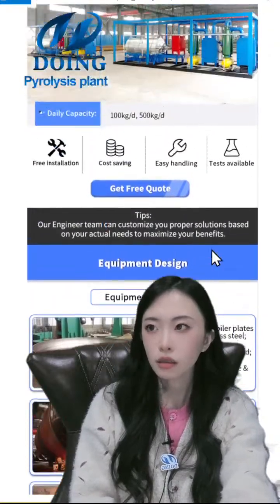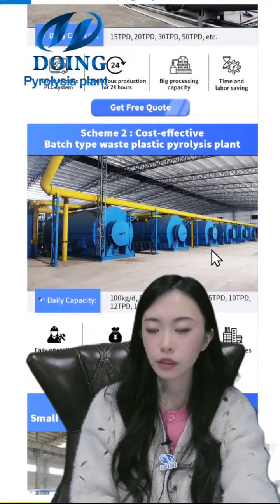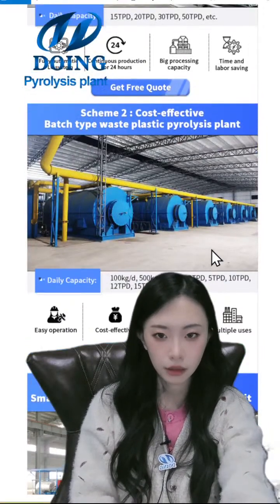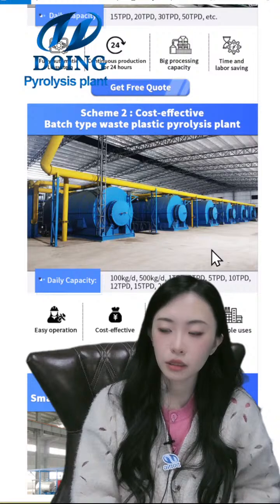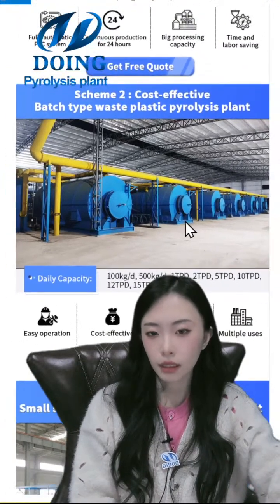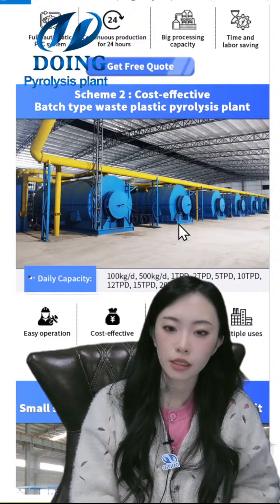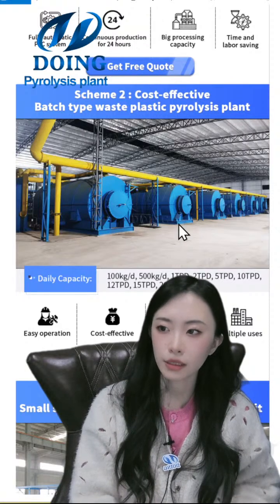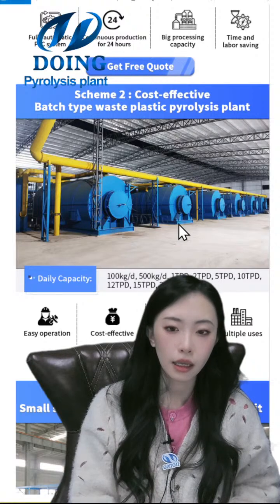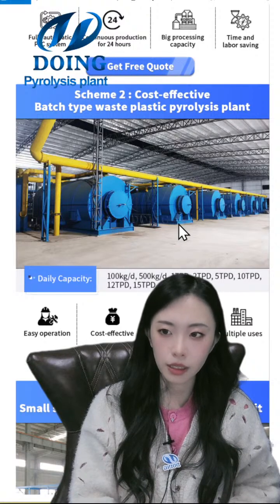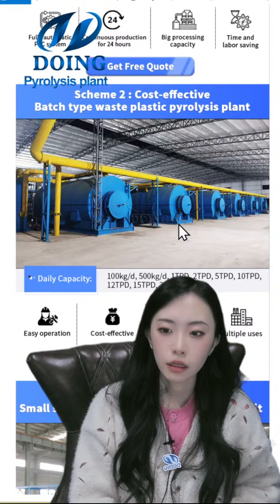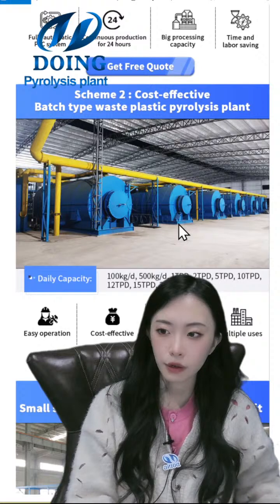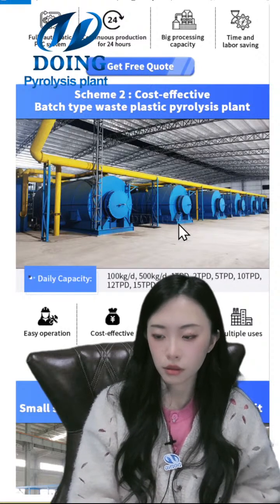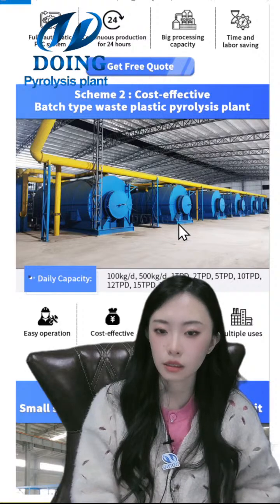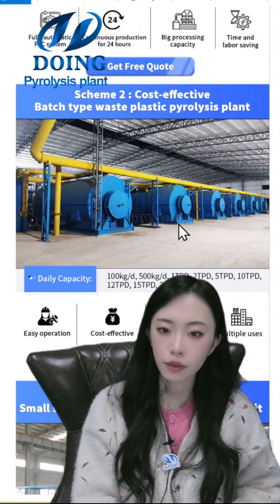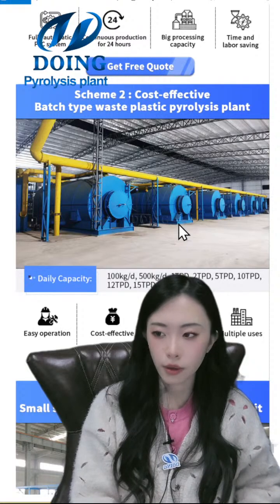And not shown in this picture, but we also have the semi-continuous pyrolysis plant. Well, the semi-continuous looks just like the batch type, but the working efficiency is much higher. The batch type gets one batch per day, and the semi-continuous one is 3 batches for 2 days. It can discharge the carbon black at a very high temperature, just 300 or 400 degrees. We can just discharge it, so it saves the time of cooling the reactor, and that is why it is called semi-continuous.